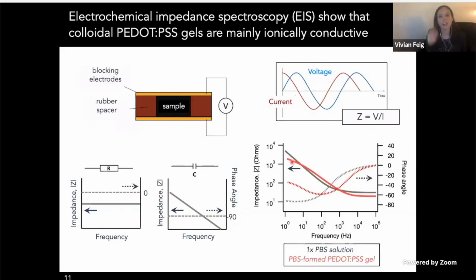And so based on this, we can see that just by forming a gel network alone is insufficient to have good electrical conductivity, and the gel that we've tested is purely just essentially an ionic conductor. And so with that observation, we were really interested to see if we could manipulate the morphology of these gels to enhance conductivity while maintaining that ultra-low storage modulus.